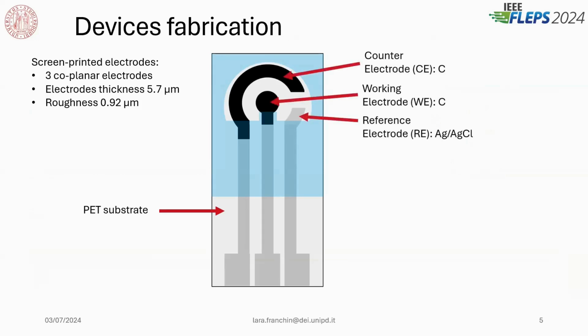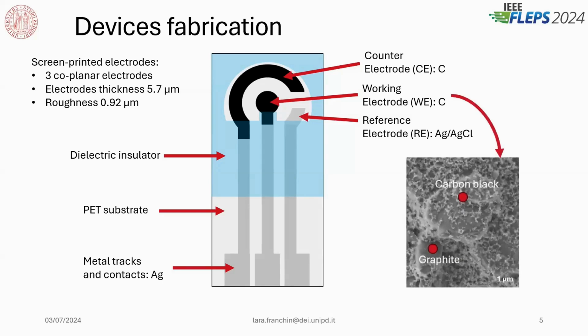So first, we fabricated the devices, which are screen printed on a flexible PET substrate, and the devices have a conventional 3-electrode structure with a carbon counter electrode, a carbon working electrode, and a silver chloride reference electrode. The metal tracks were made in silver, and finally, on top of the structure, we put the dielectric insulator to delimit the electroactive area. We also characterized the surface through SEM imaging.